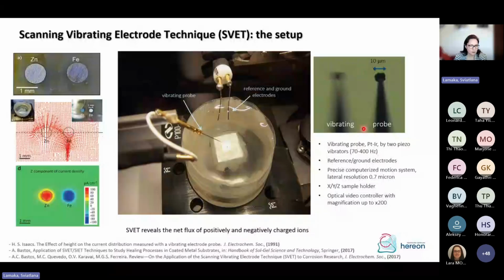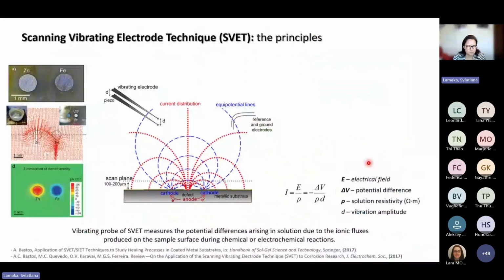Before we perform the current calibration, this is a typical view of the calibration setup. This is the vibrating probe of SVET approached to a fixed distance, normally 150 micrometers, to a point current source. In this case, it's a glass capillary, and we inject a positive current of 60 nanoampere. Before we perform this current calibration, we also calibrate the geometry of the probe vibration to make sure that there is only vertical or only horizontal vibration, since this probe vibrates in 2 planes. And after the vibration frequency and amplitude are fixed, we perform the current calibration.